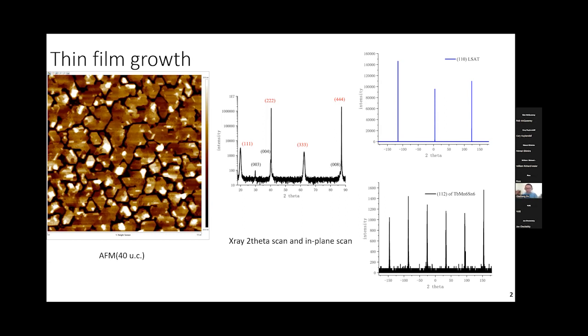Okay, so we first grow several layers as a seed layer, and then we grow the connecting layer to make the film electrically connecting. In the left panel, we can see the AFM image of a 40 unit cell thin film. The scale of the image is 5 micrometers. From the AFM, we can see the film has a smooth surface, but it's not fully connected.